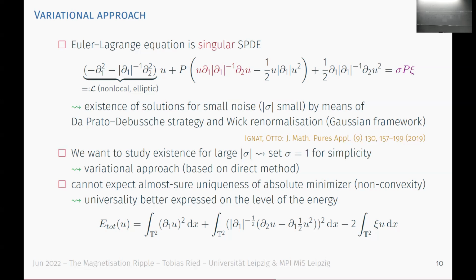So can I put it back very vaguely? Roughly speaking, when you are in the thin film and spatially far apart, there's not enough elliptic communication between the magnetizations anymore to align them nicely. And after rescaling onto a fixed domain, there's enough elliptic communication between spins that sit underneath each other in the thin film, but not far away, because then the interaction is mediated by the thin film. So I think that's a fair way of saying it.